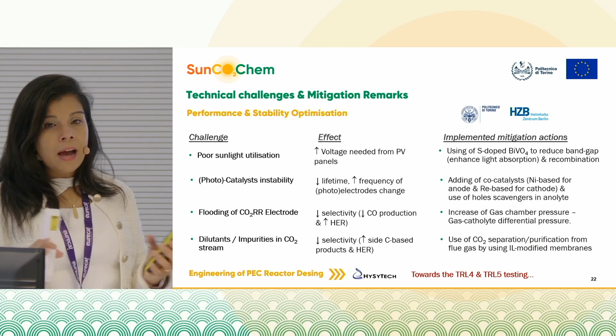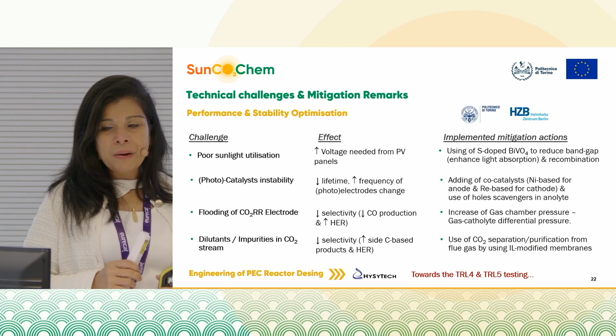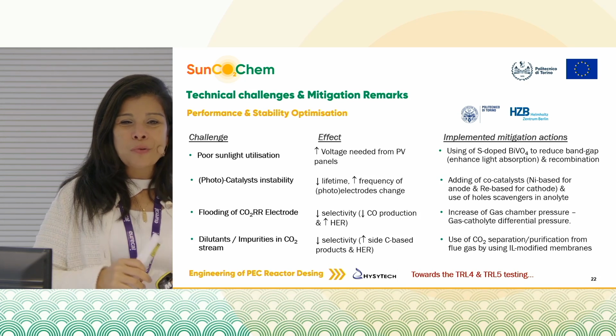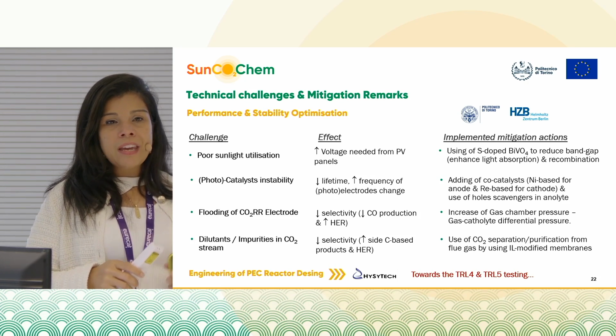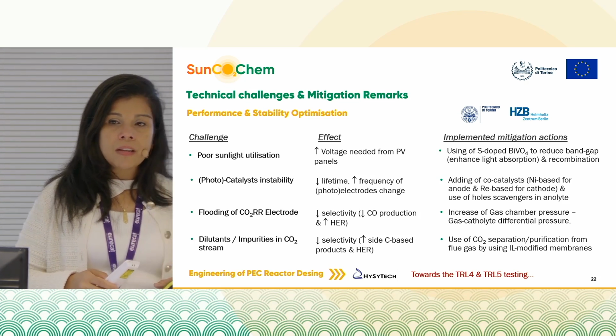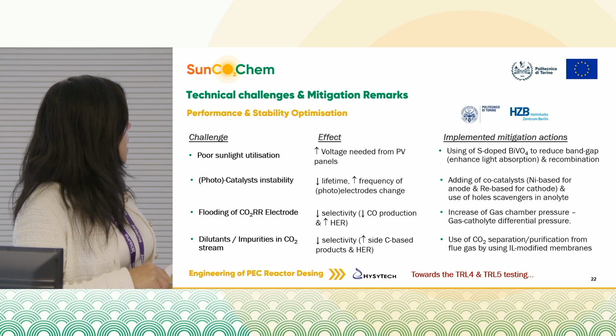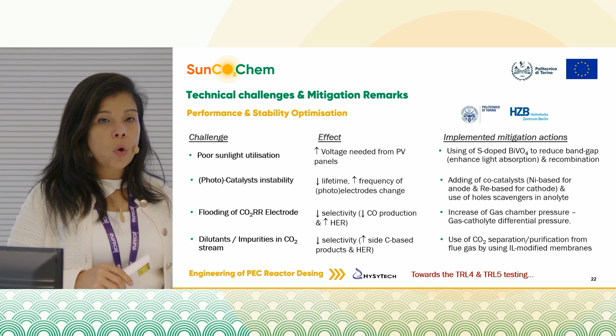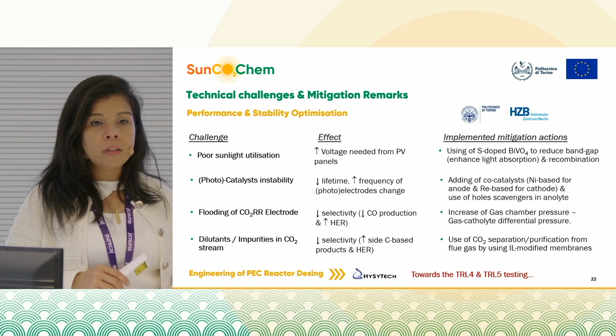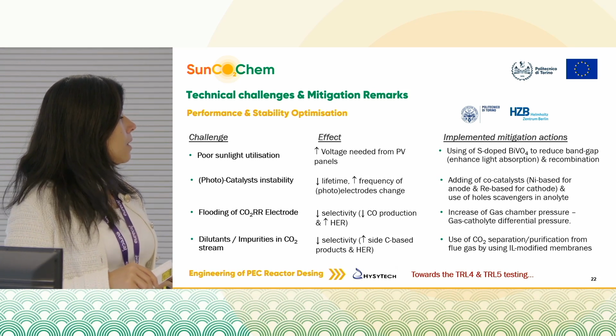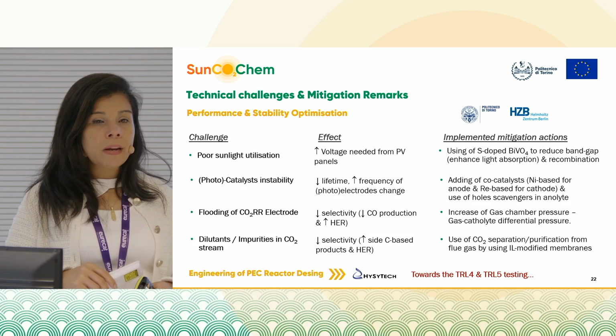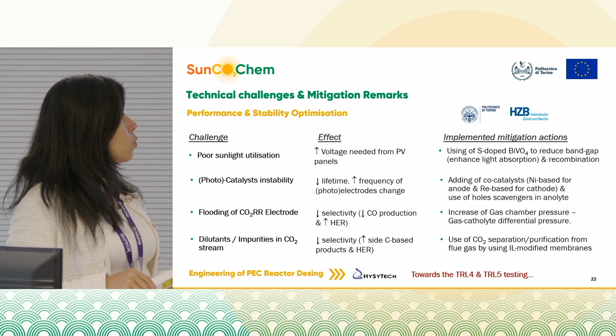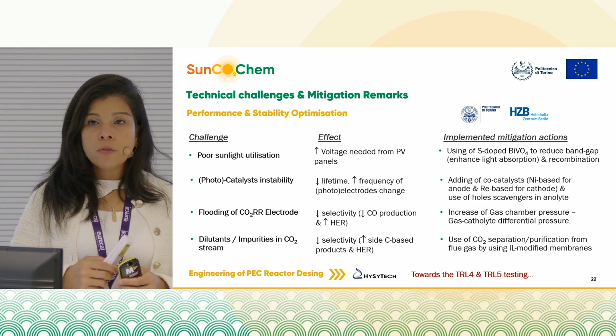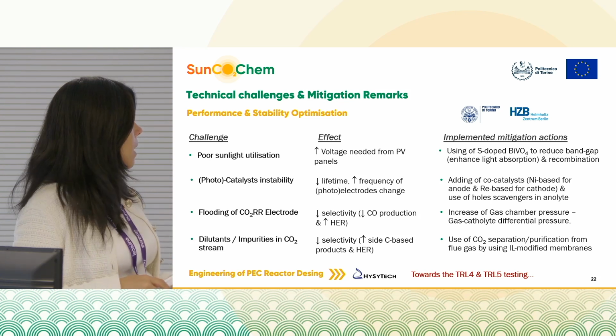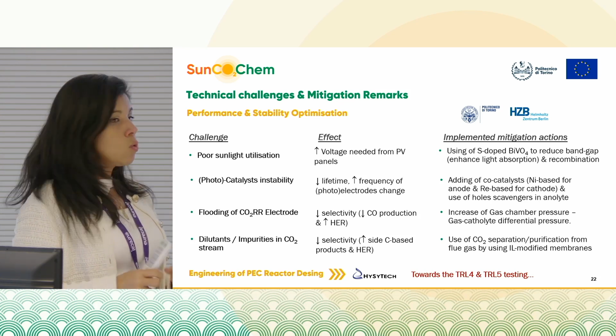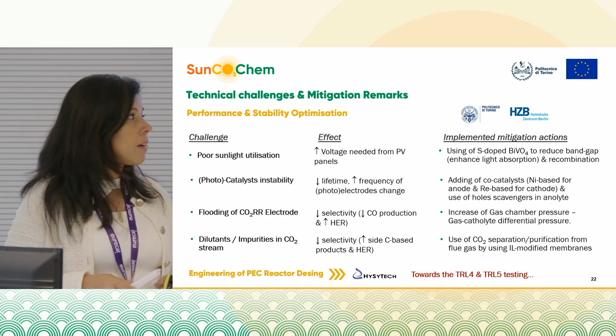So just some highlights about this very challenging process of trying to optimize our electrodes. Here you have some of the main challenges that we faced during this development. For example, the poor sunlight utilization of the photoanodes is a very critical point in this kind of research. During the project, we developed sulfur-doped bismuth vanadate photoanodes to enhance light absorption and reduce recombination of charges, so to have a better performing photoanode, and in this way reduce the overvoltage needed for the reaction.